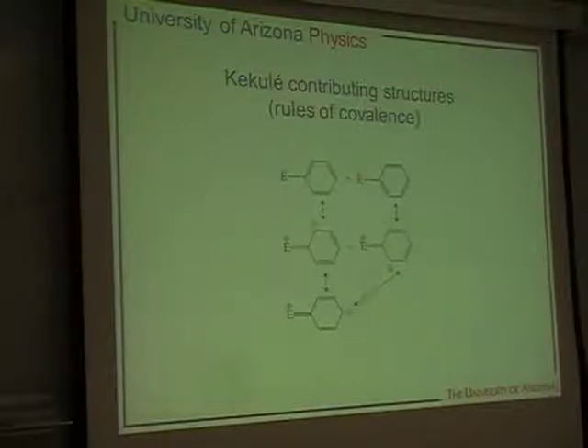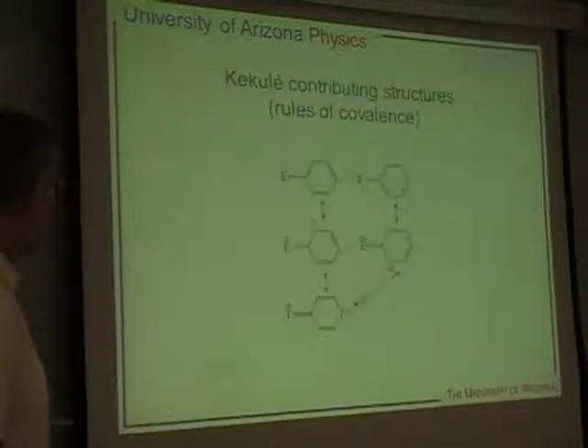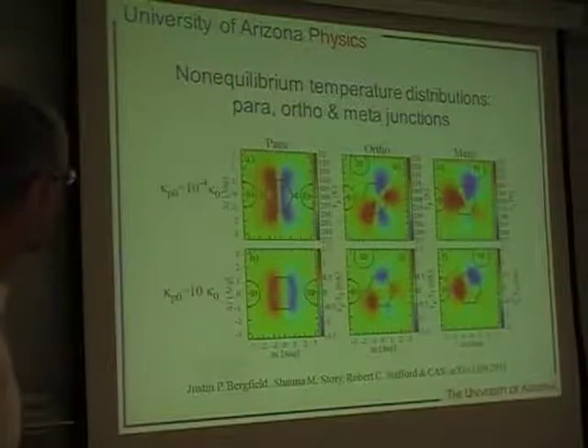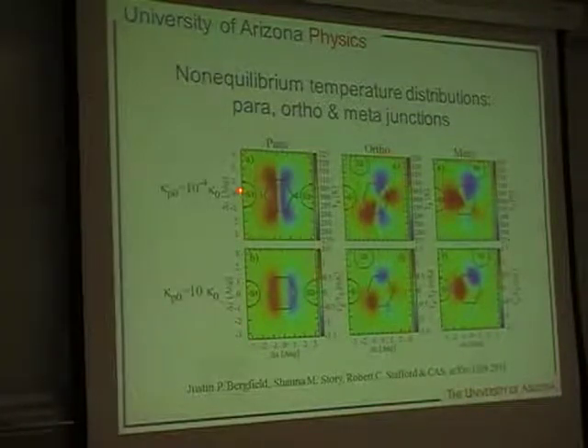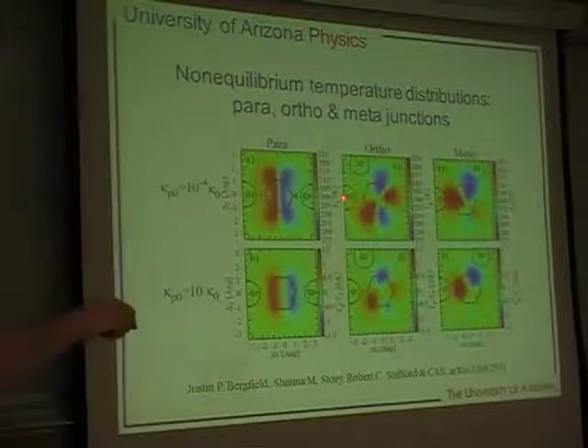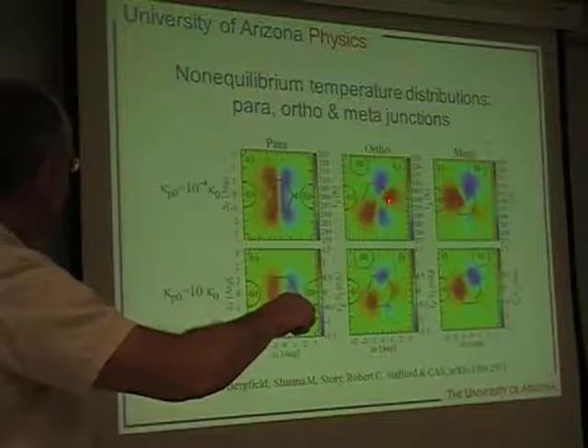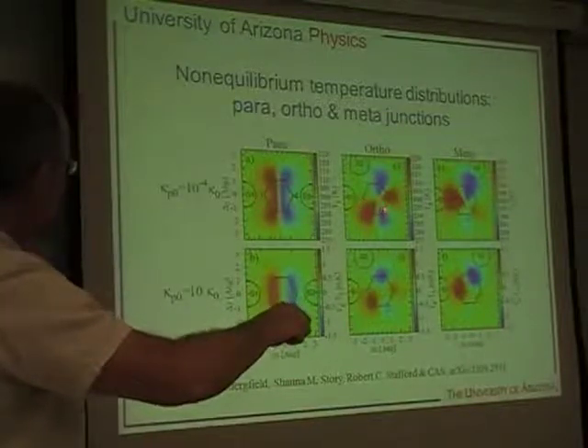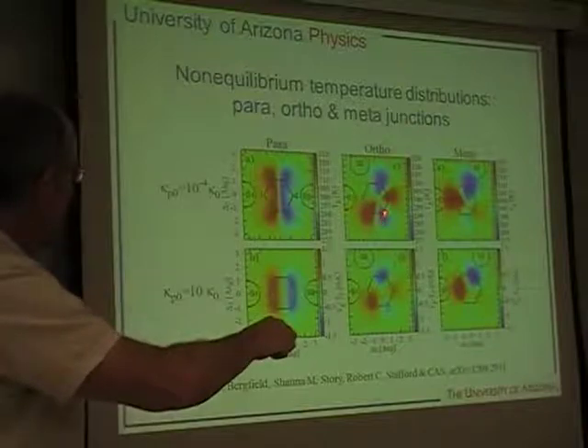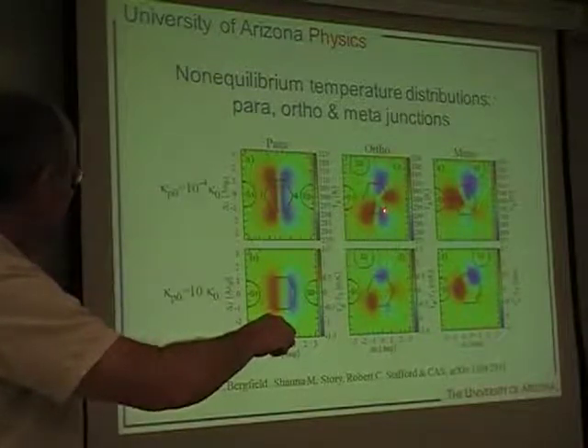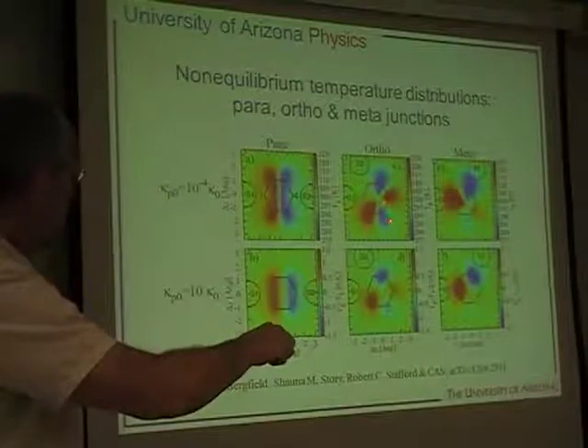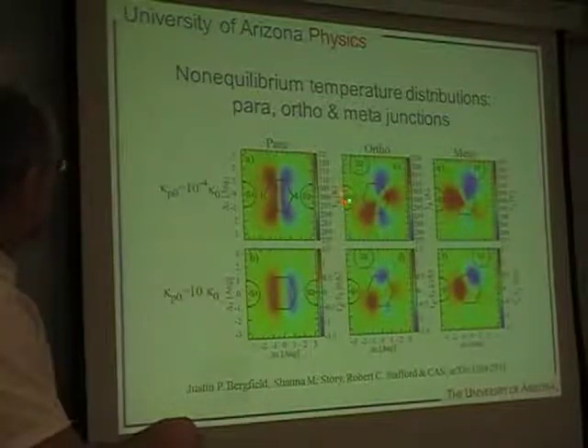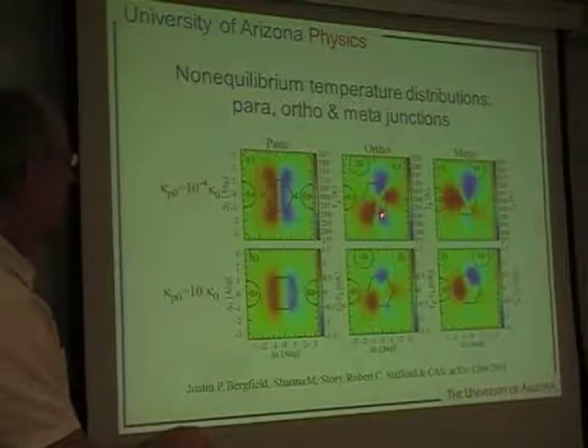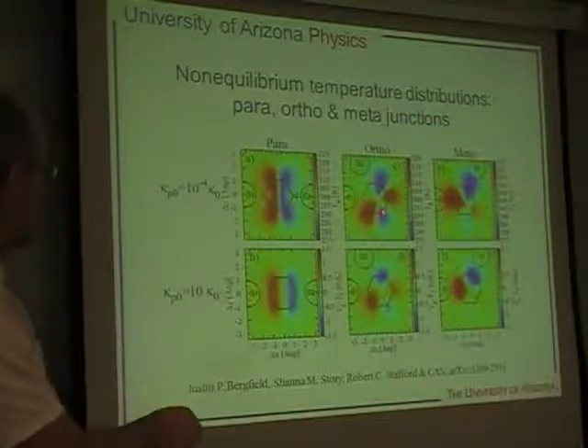So when we go back and look at this temperature, oops, I'm coming the wrong way. This kind of temperature distribution. So we say, for instance, in this one here, if the temperature probe is above, let's say, this orbital here, which is actually closer to the hot electrode than it is to the cold electrode, according to these rules that describe the electronic structure, an electron from the hot electrode simply cannot get there, even though it's closer to the hot electrode than it is to the cold electrode.